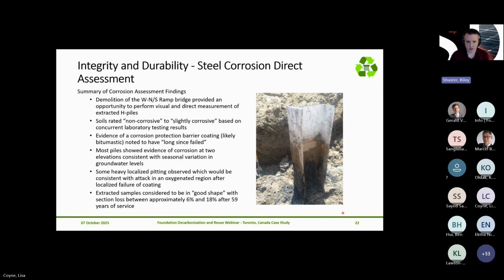So just to summarize that work, it's completed by another firm, but as part of the demolishment, they were provided with an opportunity to make direct measurements of the extracted piles, which is a really, really valuable piece of information to be able to have. Alongside that, laboratory testing was completed, and based on those guidelines I talked about a second ago, the suggestion was that the soils would range from anywhere from non-corrosive to slightly corrosive. The report notes the evidence of a former corrosion protection barrier coating that was described as having long since failed and would have been consistent with sort of bitumastic coatings that were prevalent during that time of construction.